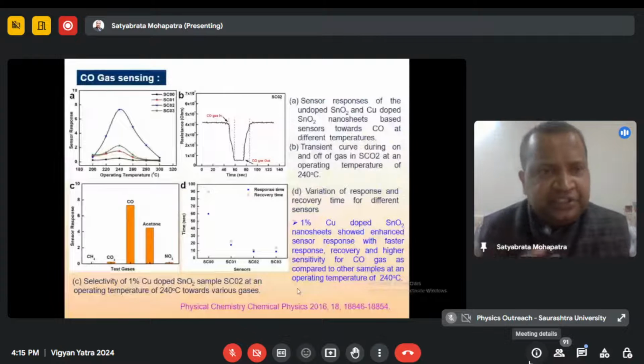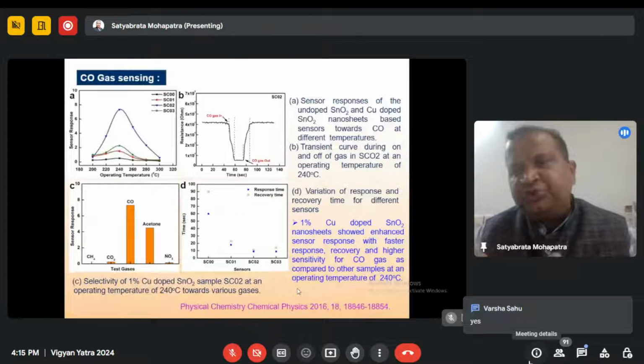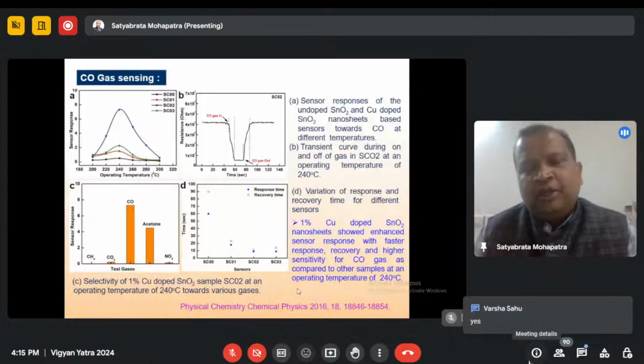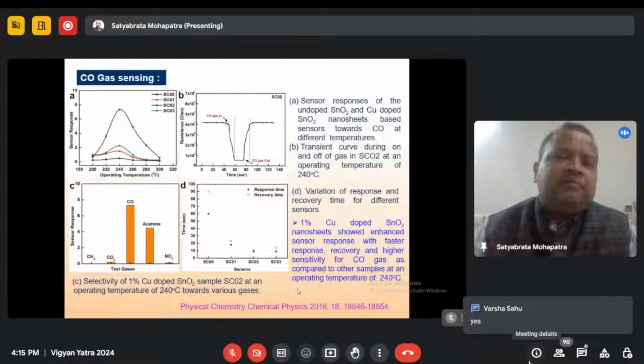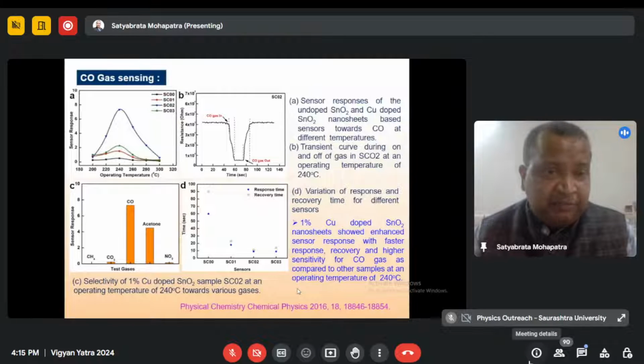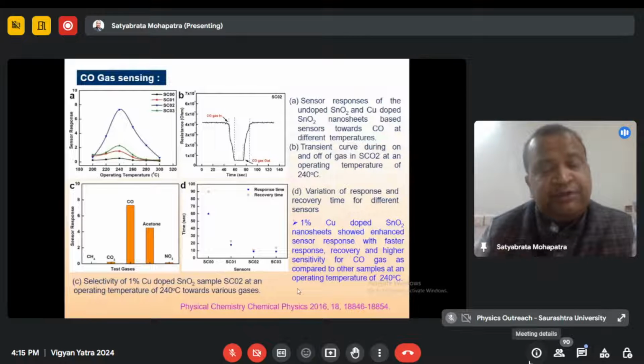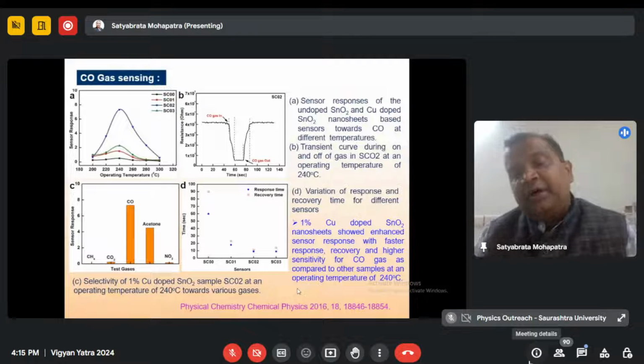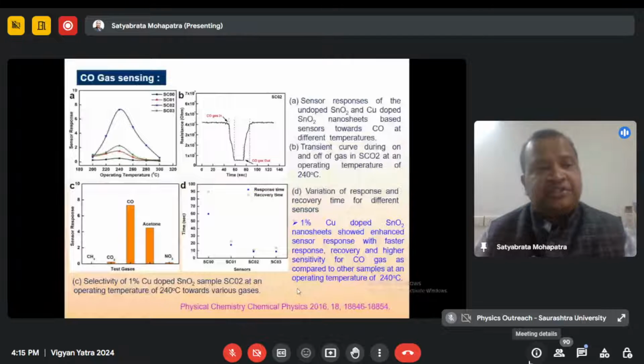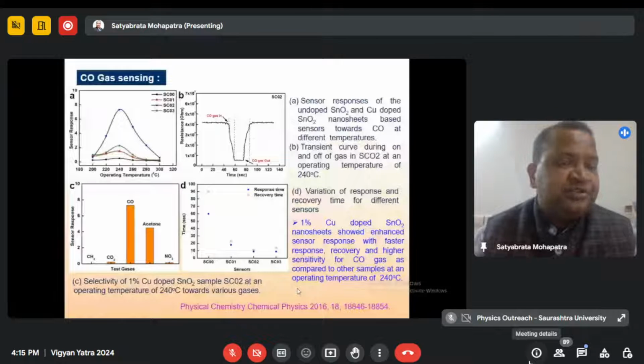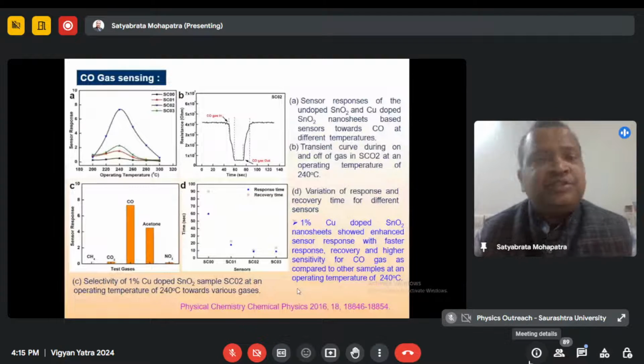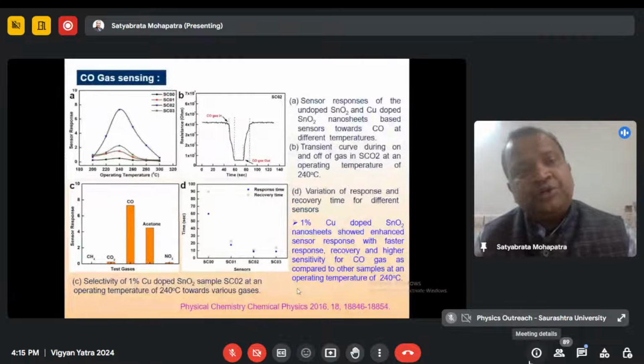And we then checked. Two-dimensional structures are interesting for any metal oxide because of the inherent high surface area they offer, and plus, if you can tailor the defect concentration or the type of defects on these 2D structures, it makes them exciting materials. So with these two-dimensional tin oxide nanostructures, optimal copper doping can improve the sensor response. That's what we wanted to check, and we went for carbon monoxide gas sensing.